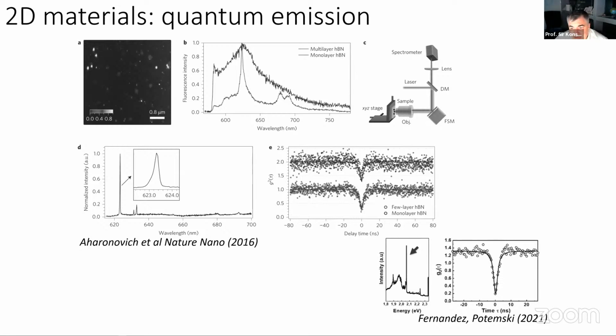So this work started with quantum dots in tungsten selenide, and now probably the most popular material is hexagonal boron nitride. And it's quite important work because single photon emitters are extremely important for quantum telecommunication. For example, if we can design those quantum dots in our materials and we can control their properties, we can produce quite complex quantum devices.